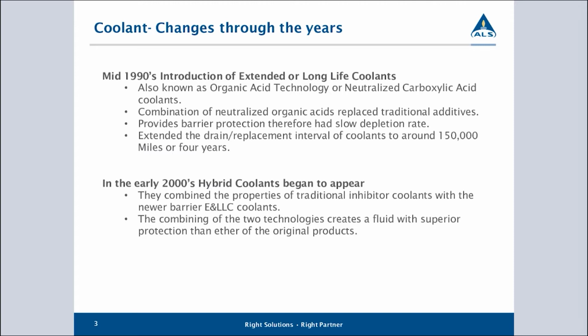That led to what we now call hybrid coolants. A hybrid coolant is simply a mixture of an organic acid formulation with a traditional, sacrificial inhibitor formulation, and you're basically trying to attain the best of both worlds. So the barrier works 90% of the time, but the 10% of the time that it gets disrupted, the conventional process will still prevent corrosion from taking place.